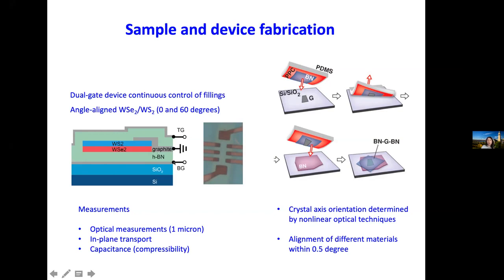The top and back gates allow us to independently tune the doping density in the Moire superlattice and also the electric field perpendicular to it. In this study, I will only discuss the doping effect because for the hetero-bilayer, there's a pretty large built-in electric field, so the electric field effect is negligible. In terms of measurement, we can send light through the whole structure and look at the reflection, and this can be done with slightly smaller than 1 micron spatial resolution. We can look at in-plane or out-of-plane transport, and we can also measure capacitance, like what Pablo described, the compressibility measurement, but not local, but global for the whole thing.